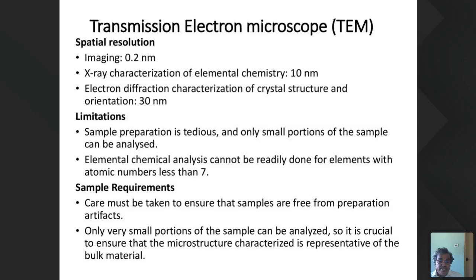What are the limitations? Sample preparation is quite tedious, and only a small portion of the sample can be analyzed. Unlike SEM, where a larger sample is possible, even a large size can be accommodated, here it's not like that. Elemental chemical analysis cannot be readily done for elements with atomic numbers less than 7. That is another important limitation of TEM.